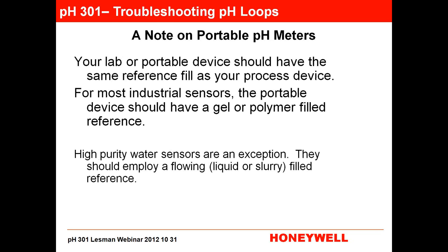Okay, I was talking earlier about doing calibrations and comparing apples to apples, etc. A note on portable pH meters that you can use to do your grab samples. Your lab or your portable pH sensor should have a reference technology that is similar or the same to the reference technology that you're using in your process. I would say that most of the time in your process, unless you're in a high purity pH situation in a power plant for boiler water, your pH sensor hopefully has at least a gel fill or a polymer. Maybe it has a solid type reference like DHB. So you would want your portable to have probably a gel or a polymer type reference fill as well.